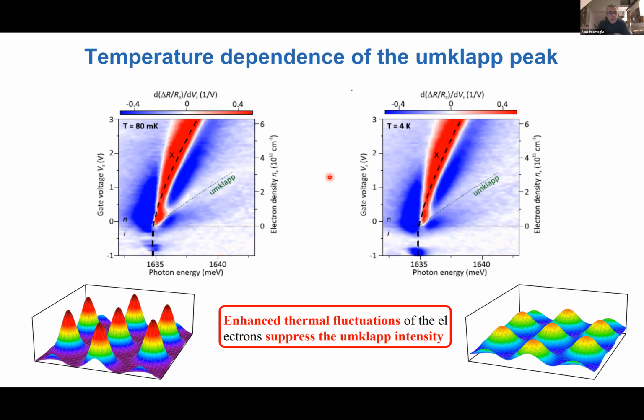Sure, thank you. So thanks a lot for the detailed explanation. I thought these measurements were done at high magnetic fields at 14 Tesla. And I shared the reference. This is the work done by Tony Heinz. They were applying a magnetic field to see the dark excitons, and they see a new resonance appearing. I was just curious if the features that you're seeing could be due to dark excitons becoming optically accessible.